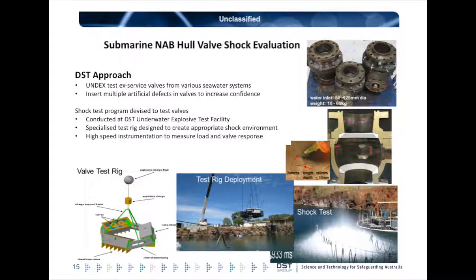One issue we were worried about with the Collins class hull valves is that they do corrode and they replace them every 3 years. So the concern was what happens if we get a shock loading and you've got a corroded hull valve. So, for instance, some of the tests we've typically done is to have some full thickness sections of hull plating with a number of valves mounted in them, and we can put an explosive charge above that, lower it underwater, and actually load the valves up to their full design level that they're expected to survive. And I guess the outcomes of that test was that those corroded hull valves did survive